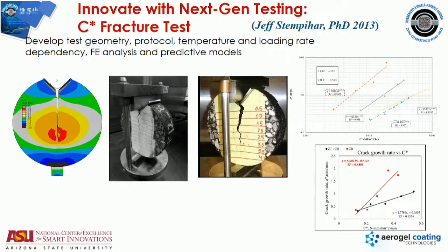So innovate with next generation testing. Again, there are great standard tests out there, but don't be afraid to try new tests. This is what we have done at ASU, and actually this is back in 2013, very well documented by Jeff Stempihar. C-star fracture test, adopted from engineering mechanics that they use on metals, right? But we converted everything to use for asphalt mixtures. It's a simple test that helps us understand crack propagation, how fast these cracks develop in the mixture, and the amount of energy needed to drive that crack. And guess what? Asphalt rubber mixtures have done great in this test as well. We use this one for fibers. I do a lot of work with fibers, and this is really a great test that we have been doing and so forth.